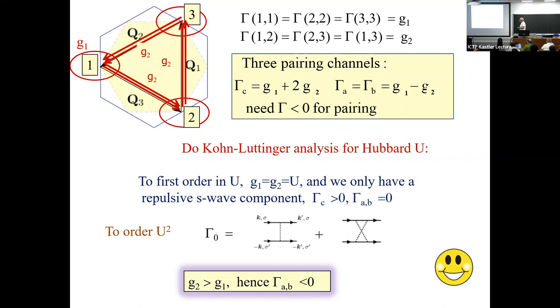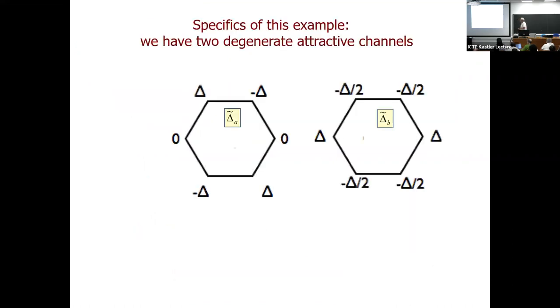Same story, but there is a twist. The two are degenerate, and degenerate by symmetry. As a result, you will get two different orders which develop simultaneously. In D wave formulation, both have four nodes. One is the analog of dx square minus y square, the other is dxy. They're degenerate by symmetry. And then you ask when they develop.